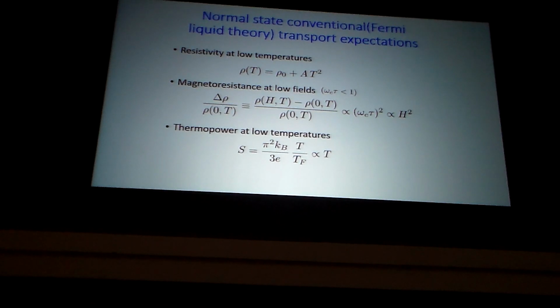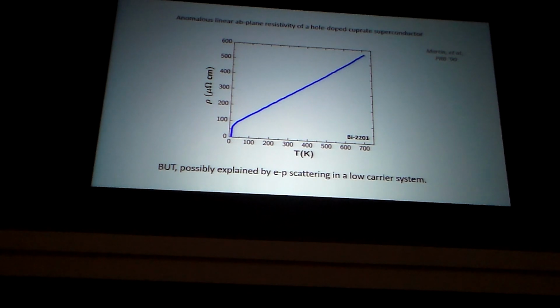So what did we actually find when we measure the cuprates? I'm going to show you what we find in some of the cuprates. First of all, a long time ago, in the normal state of this cuprate, linear in T resistivity was found down to about 8 kelvin. Now, as Shankar said, if you have electron-phonon interactions, then you expect to get a linear in T resistivity caused by electron-phonon scattering in the normal state.